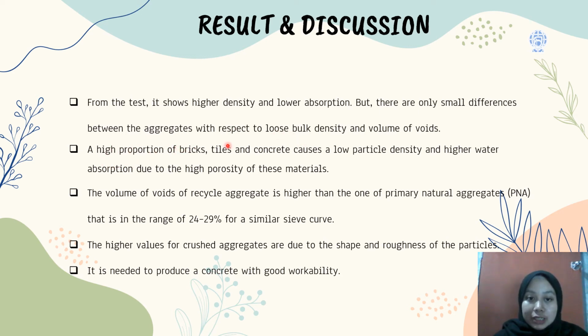A high proportion of bricks, tiles, and concrete causes a low particle density and higher water absorption due to the high porosity of this material. And then the volume of voids of recycled aggregate is higher than that of primary natural aggregate, which we label as PNA, which is in the range of 24 to 29% for a similar sieve curve. The higher values for crushed aggregates are due to the shape and roughness of the particles. It is needed to produce a concrete with good workability.